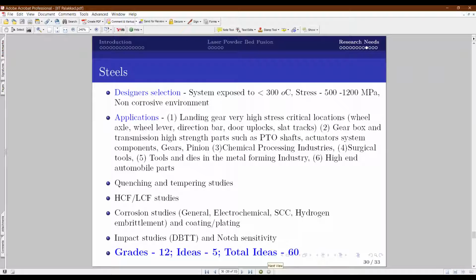Steels are generally prone to various forms of corrosion, so studying electrochemical and stress corrosion cracking and hydrogen embrittlement is very important, and schemes like coating or plating to avoid, minimize or delay corrosion need to be studied on these 3D printed steels. And impact studies are another important area, because steels are prone to ductile to brittle transition, and steels are notch sensitive. So similar to titanium, we should also understand the stress concentration effect on these steels.